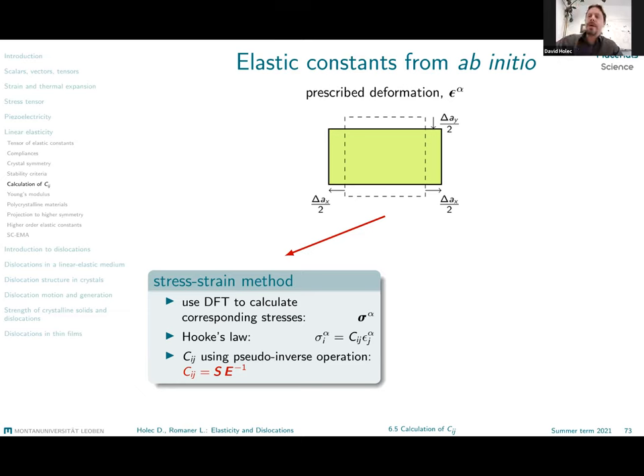stress. If we do this for a certain deformation mode, we get a set of stresses. The index I or J here represents the Voigt notation. So both of these objects which are circled here are 6 by 1 vectors. Alpha represents the fact that I prescribe a certain deformation. Maybe this is a tetragonal deformation, tetragonal elongation by 2%. Maybe this is a hydrostatic pressure, hydrostatic deformation. Whatever you decide. For a given strain, you get a given stress.